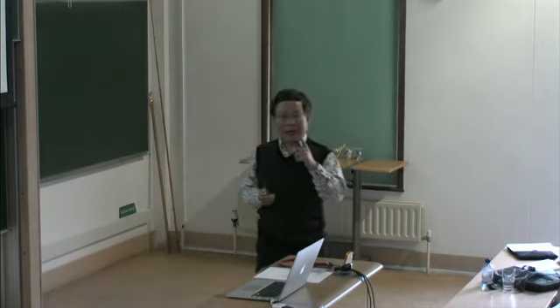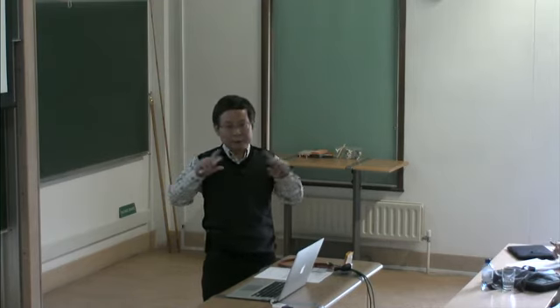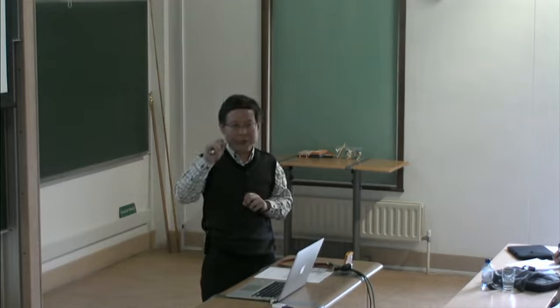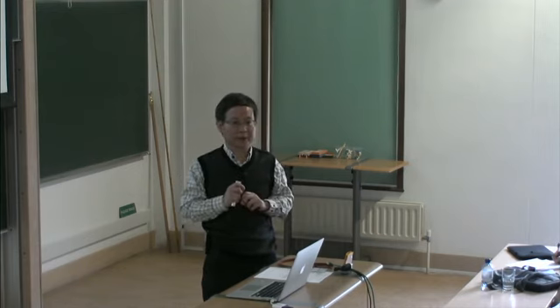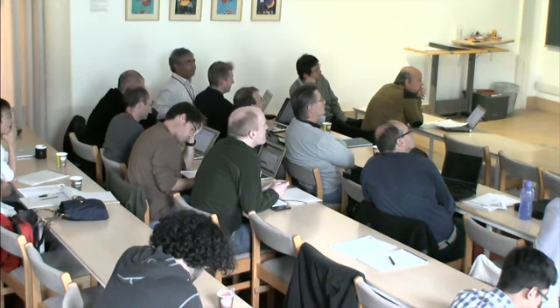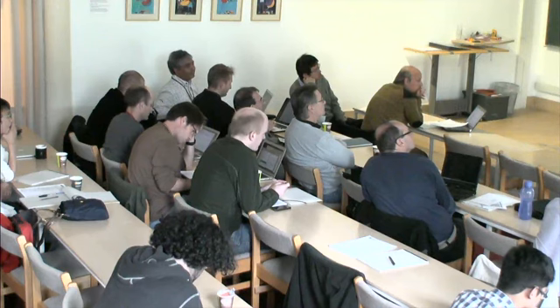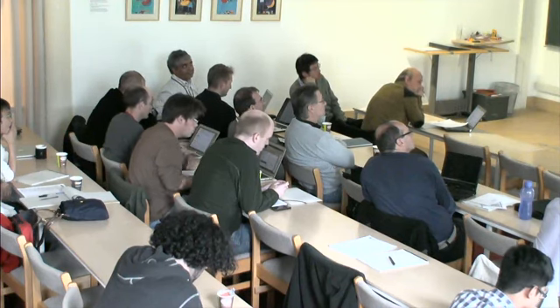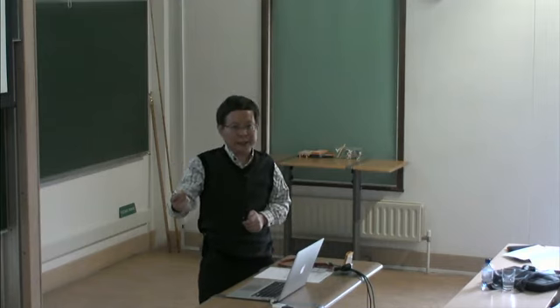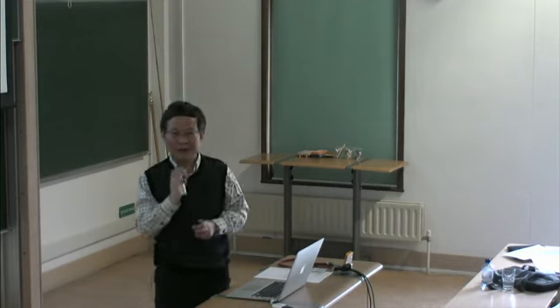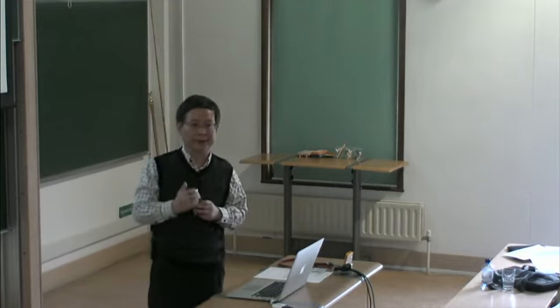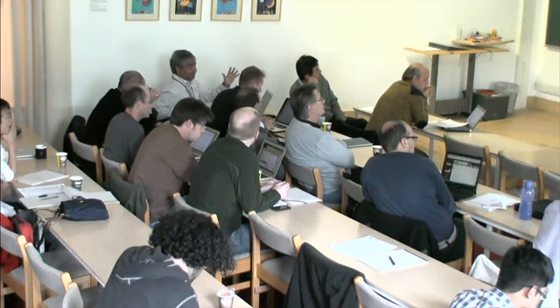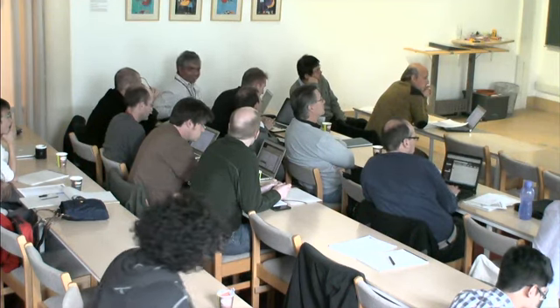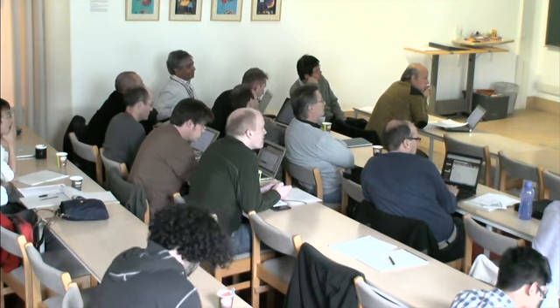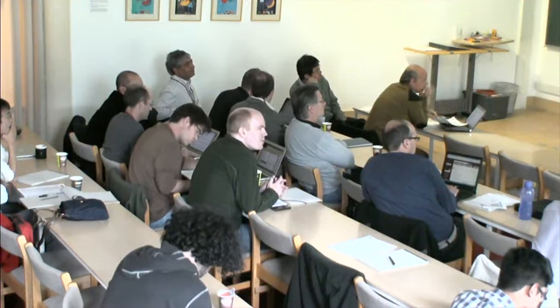Yeah, but the same argument can be applied to the ladder case. As we showed in the ladder case numerically, you see this sign structure is really non-perturbative. I have trouble with the ladder conclusion too, but here it's a simpler case. Yeah, so here there is order. But self-consistently you assume there's a quasi-particle weight, but experimentally, in photoemission, all things tell you that the quasi-particle weight is really broad. I agree, if you have finite density, all kinds of strange things can happen. No, one hole. Starting from a half-filled sample, they use a photon to knock one electron out, and that's one hole. This is a really broad feature.